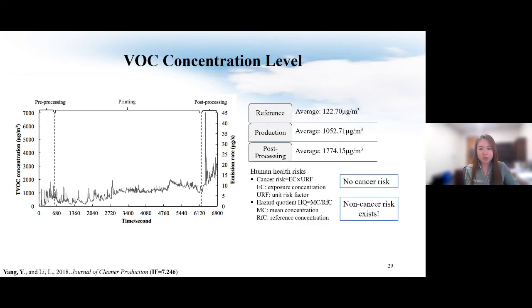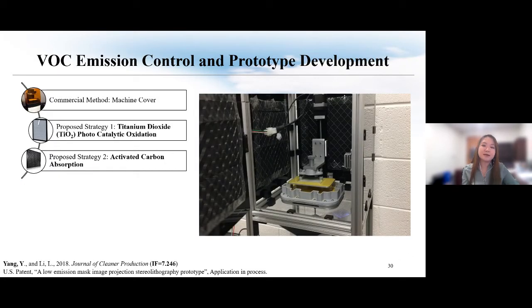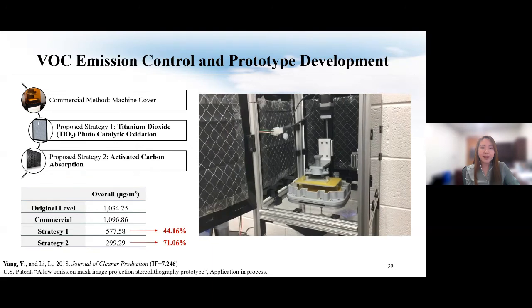So after the evaluation, our results show that there's no cancer-related risks, but there are definitely some non-cancer risks like skin irritation, lung problems. So the next step here is, what can we do to reduce that emission and make the printer more environmentally friendly? Well, the commercial method is just to add a machine cover, which has been proven to be not that effective. So we tested 2 methods. One is to use titanium dioxide to oxidize the VOCs, and the other one is to use activated carbon to absorb the VOCs. Both methods turn out to have the ability of reducing the emission level by a significant amount.